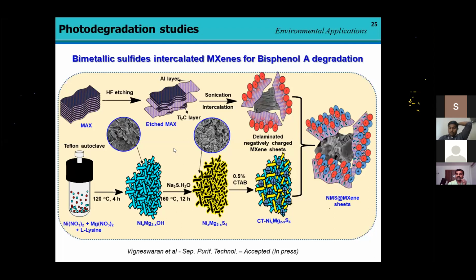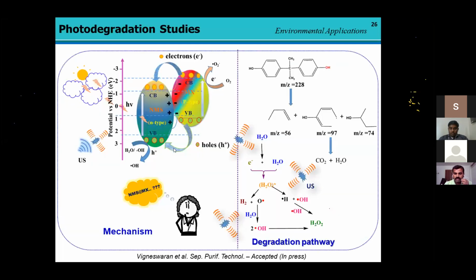Sulfur is more beneficial for degrading other materials, also due to its electronegativity. Then this material was combined with the help of some surfactant. Then we found that this material is highly effective at degrading bisphenol A. This was confirmed by the ESR results. Then this paper was accepted. This is the main mechanism behind how bisphenol A is degraded.